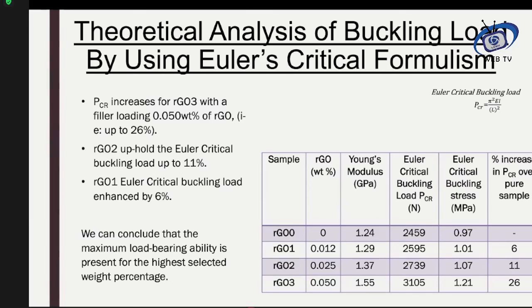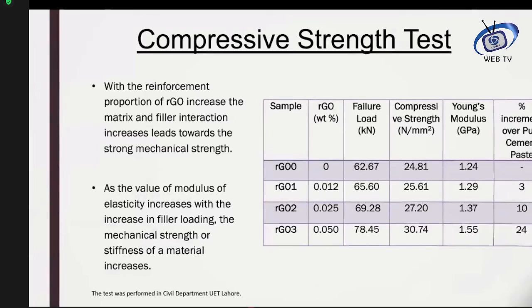The Euler buckling load was calculated in newtons, and that PCR value shows that the controlled sample has a load of 2459 Newton, which has been enhanced with the inclusion of RGO to 3105 Newton, a percentage increment of 26%. So in comparison with the control sample, a 26% enhancement in the critical buckling load was obtained theoretically, which was in agreement with the experimental one. So they were more or less close to one another. Around 26% was obtained theoretically, and around 23% in the machine testing analysis.